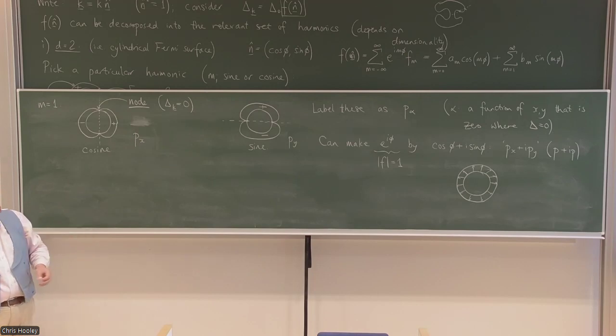Yes, this was a strontium ruthenate in-joke, and it probably won't be the last. But the serious point is, they see this time-reversal-breaking signature over a huge range of superconductors where there's no real reason at all to see it. So you would falsely conclude that your argument here was correct, if all you had was muon stuff.